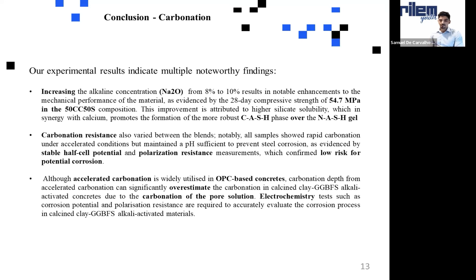So the main conclusion is that although accelerated carbonation is widely used for OPC concrete, the carbonation depth from accelerated carbonation can significantly overestimate the carbonation in calcined clay, GGBFS, alkali-activated concrete, and normally all geopolymer concrete. So electrochemistry tests such as corrosion potential and polarization resistance are required to accurately evaluate the corrosion process in geopolymer concrete, and in our case, the calcined clay GGBFS alkali-activated materials.